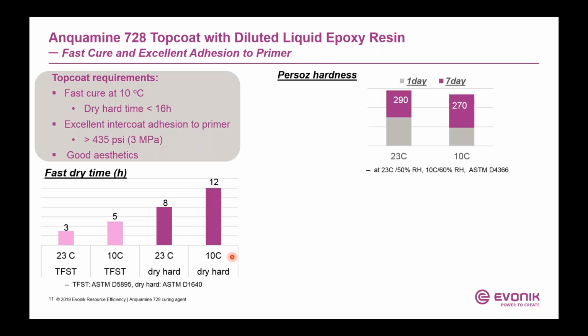For the top coat, as I emphasized in the starting point formulation, the top coat is based on dilute liquid epoxy resin. So the top coat has a thin film dry time at 10C of 5 hours, and then has a dry hard time at 10C of 12 hours, and then it has a pretty good property buildup at 10C and ambient temperature.